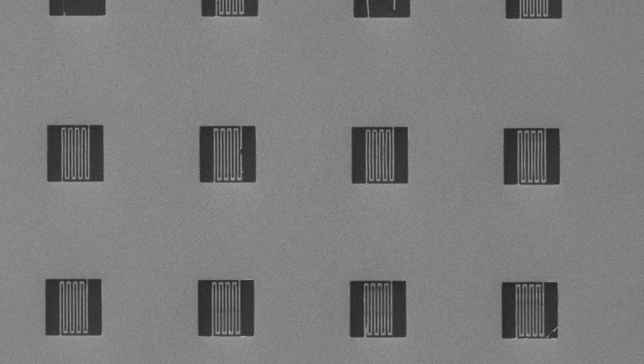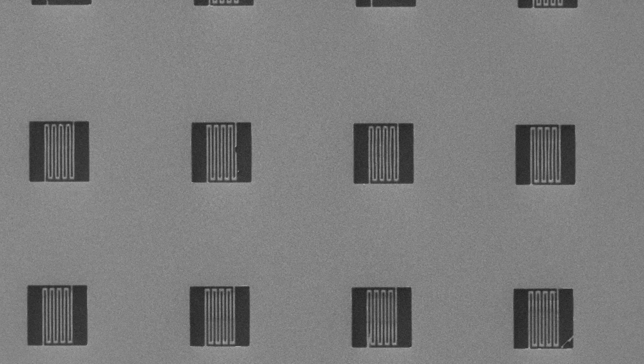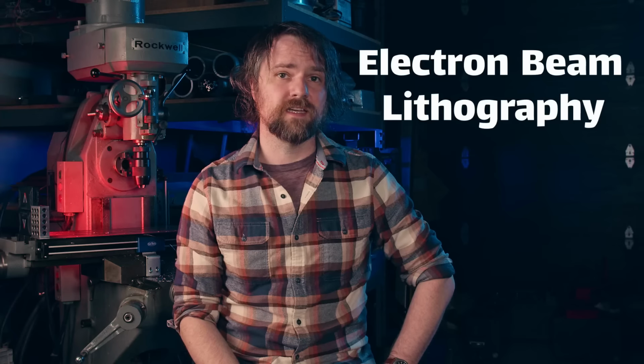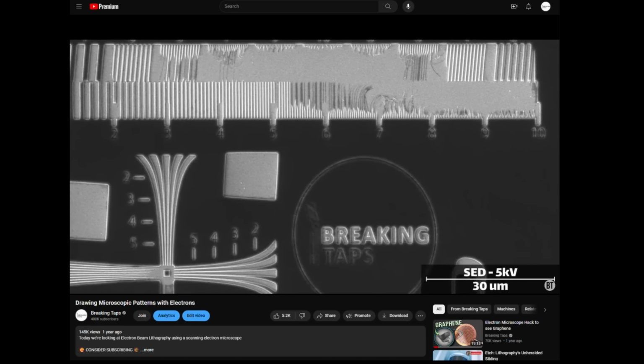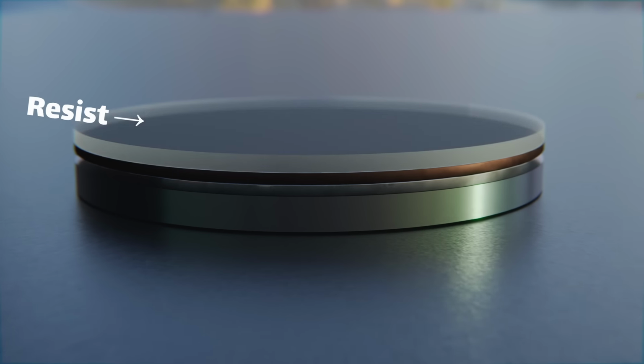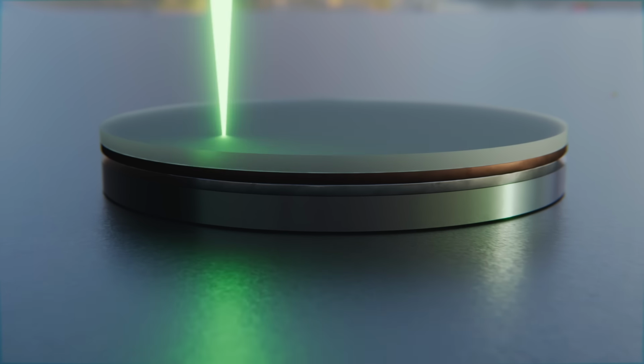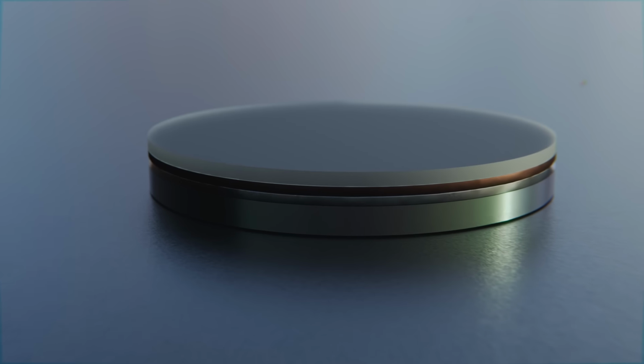And most importantly to me, they are single layer devices, which means we can pattern them directly on top of the semiconductor. So fabrication is pretty simple, which means the next step is to actually make those electrode patterns. To do this, I'm going to use electron beam lithography. I've made a video about this in the past, which you should totally go watch. But essentially, we're going to use a resist material that is sensitive to an electron beam, then scan a beam across the surface to develop a pattern.